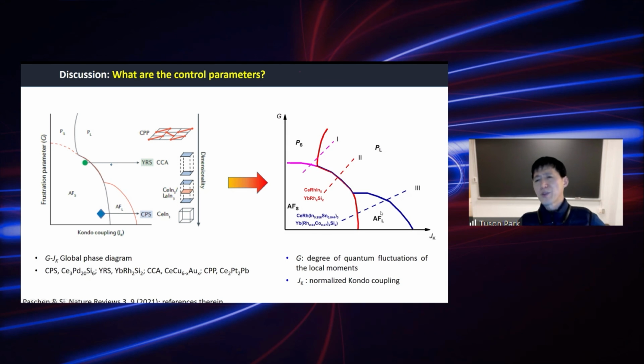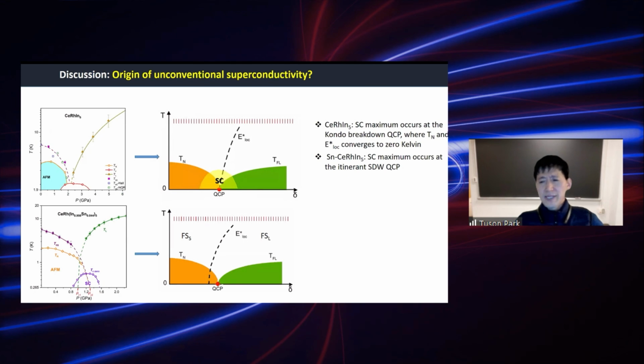going through this path. And the superconductivity, I think I have maybe 3 minutes or so, I'm going to briefly wrap up my talk. Here, the superconductivity in cerium rhodium indium 5 is a very rare example of a quantum critical point where we suspected that not only spin but also charge degrees of freedom are involved in producing superconductivity. However, the tin doped compound clearly shows that the spins are involved in producing superconductivity, not the charge degree of freedom. So this suggests that we can rule out the scenario of charge fluctuation or valence fluctuation.